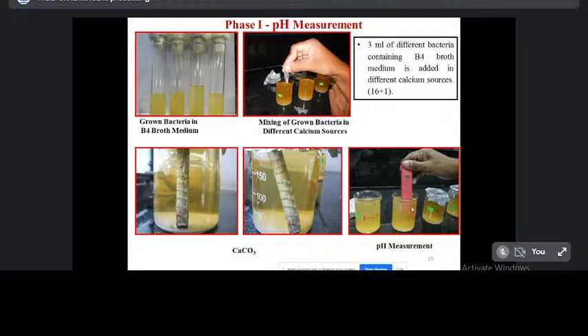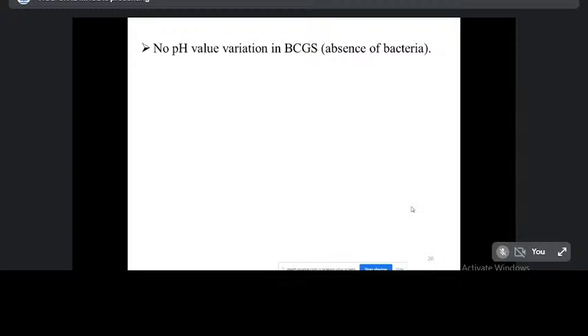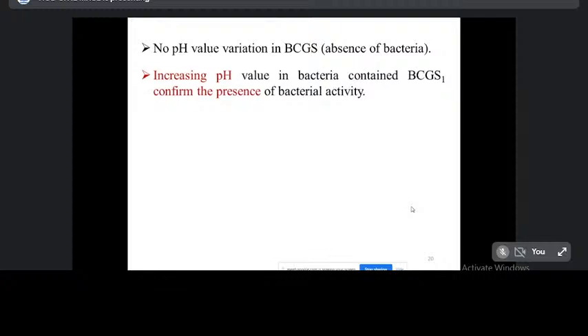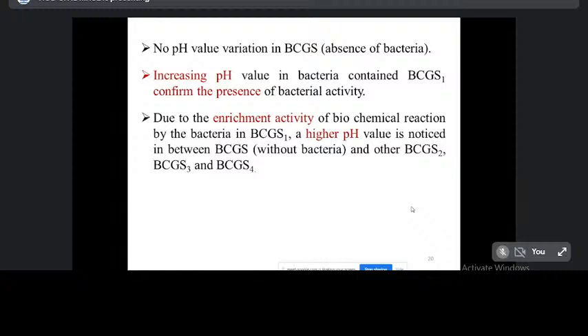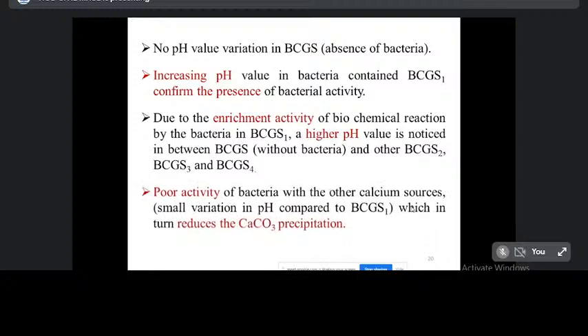Actually, bacteria mixed calcium source shows a higher pH value as compared to the normal solution. This is the observation. No pH value variation in BCGS1, right? The pH variation is constant in the absence of the bacteria solution. Increasing pH value in bacteria-contained BCGS1, that means 8 gram nutrient broth, 2% urea, and 25 millimole of calcium hydroxide solution, shows a high pH value due to the enrichment activity of the biochemical reaction by the bacteria in BCGS1. A higher pH value is noticed between BCGS without bacteria and the other BCGS2, S3, and S4. Poor activity of bacteria with other calcium sources shows a small variation of pH compared to BCGS1, which in turn reduces the calcium carbonate precipitation.